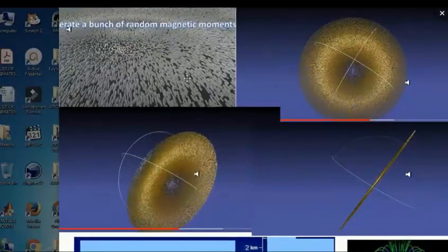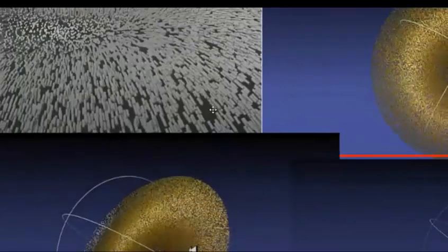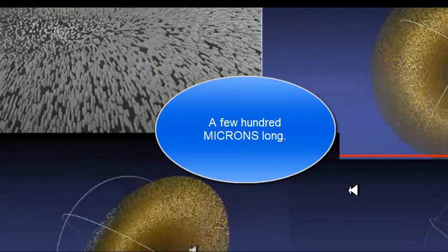So the input of this specific simulation used is not correct because, first, the density here is too large, it's ridiculously large. In a normal ferrocell, the volumetric percentage of the nanoparticles compared to the solution which they're in is 0.2%. It's very high here, and we cannot know the exact paths of the trajectory the nanorods are taking, because you see the nanoparticles, which are spherical, are joining and forming these nanorods. The nanorods are about a few hundreds of nanometers long, but the nanoparticles themselves are only 10 or less nanometers.